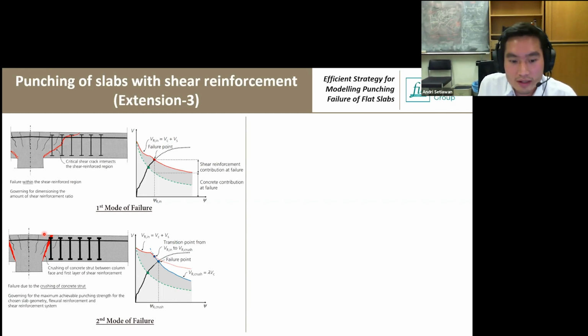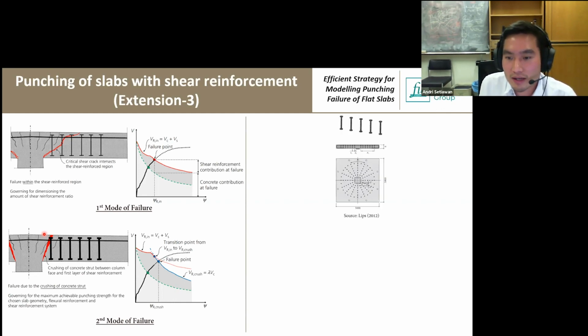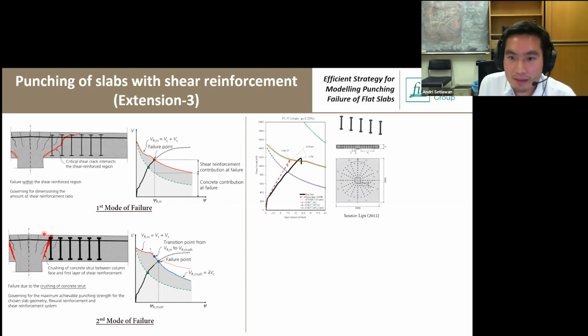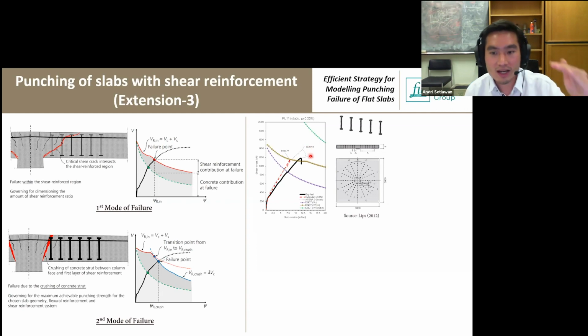So we do the modeling. The first one is the test of isolated slabs reinforced with headed studs. We model two different slabs. The first slab is PL11 with a lower reinforcement ratio, 0.23%. And as we can see here, the black curve is the test, the dotted gray is the Athena, and the red curve is the model that we have from our proposed model. So we can see here that the governing failure criterion is the inner one, which is basically the first mode of failure. This is consistent with the saw cut of the slab after the test, where we see the crack is cutting the shear reinforced region.